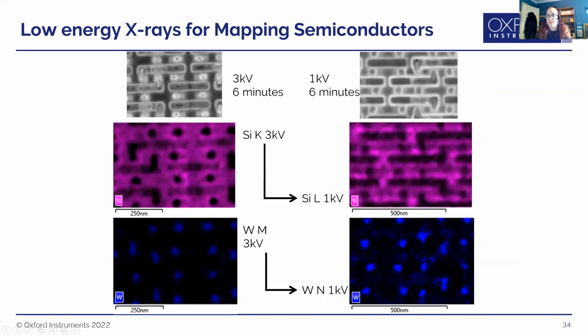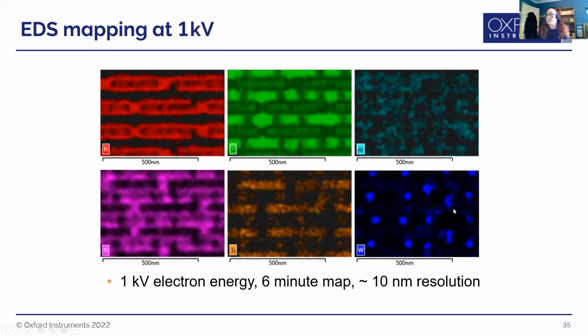And we can go even further, and if we go even further down to 1 kV, we're making absolute sure we're just getting really surface information. And you can see the difference in the electron images here. They're not quite the same region, but they're an analogous region. So you can see the difference. We're getting much more surface information. We're getting much better surface information from both the silicon and the tungsten here. So we're getting much better signal. You can actually see in the tungsten, we're getting much clearer signal as well, because we are just limiting it to that surface information. And this means we can get really accurate data.